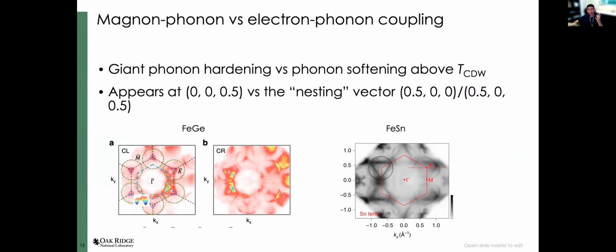Before we move on to a detailed theoretical calculation, I want to make another comment about the magnon-phonon coupling versus electron-phonon coupling. Another reason, I should say, that motivated us to exclude the nesting picture is a comparison of two similar materials: one is iron germanium and one is iron tin. Both of them have A-type AFM, and if you check the band structure, they are remarkably similar. They have the same Van Hove singularity near the M point, but still one has a CDW, one doesn't. So that indicates that nesting doesn't really work for iron germanium.